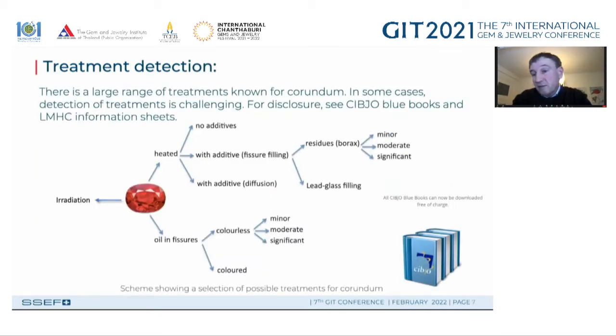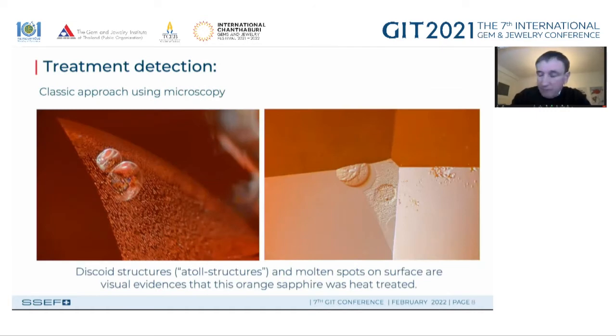The next step is to talk about treatments. Now, treatments, everybody knows there is a large range of treatments known for corundum. And for some of these treatments, the detection is not straightforward, but rather challenging. So to go into detection of treatments, we again have access, and this is a very aesthetic side of this work also, to microscopy. That is very important, and as you can see here, these are very classic inclusions which we see, so-called atoll structures in an orange sapphire, and even on the same stone, some parts where you see a molten surface. So this stone definitely is heat treated, which we can tell by microscopy.